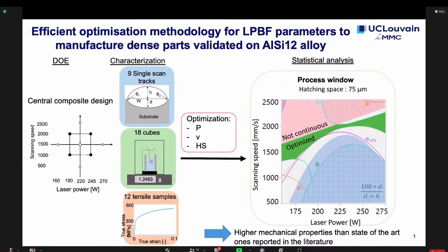The density will have influence on the mechanical properties, mainly on ductility, but the LPBF parameters will also influence the melt pool geometries and the microstructure, so the size of the cells, and all these will also have influence on the mechanical properties. So we directly make the link between the LPBF parameters and the mechanical properties without really seeing if it's the microstructure or the density which has influence, but both have influence.